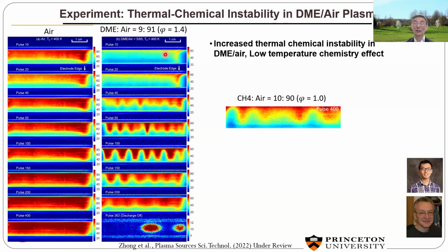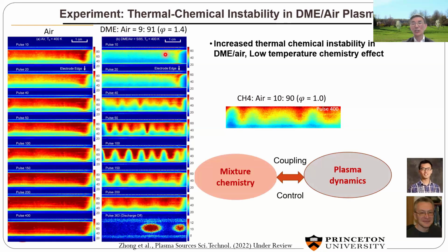This is a very encouraging observation, because the combustion chemistry affects plasma instability, and then the heat generated by the combustion also stabilizes the flames. So this observation completely changed people's thinking. People always say plasma chemistry and plasma dynamics are very short, in nanoseconds and microseconds, and combustion is always dictated by plasma. But our experiment and theory tell people that combustion chemistry can change plasma dynamics and modify plasma chemistry as well. So this provides a great opportunity for combustion chemistry or oxidation chemistry to play a role in plasma.